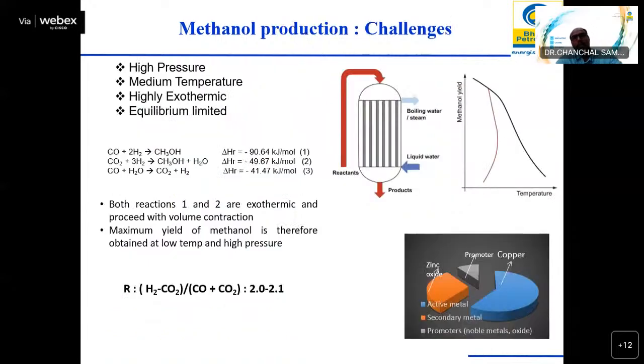So the methanol production process has inherent challenges. This is an exothermic reaction, equilibrium limited. So the per-pass conversion for syngas to methanol is limited to 15 to 20%. Also, catalysts operate in a very optimum range of temperature. If there is high temperature and there is no efficient removal of heat during the exothermic reaction, then the catalysts suffer irreversible damage. So that's why a methanol reactor needs to be operated in a very narrow range of temperature.